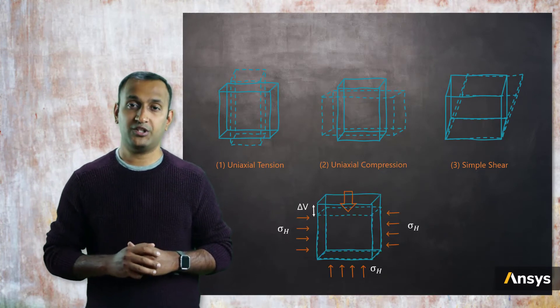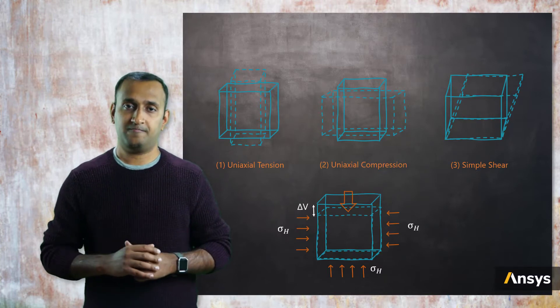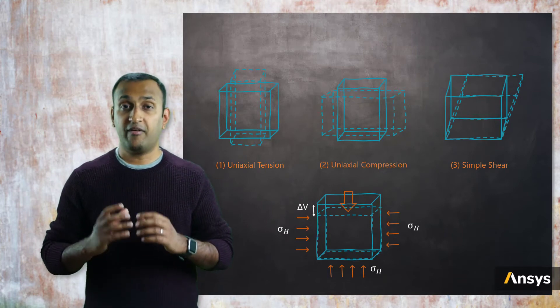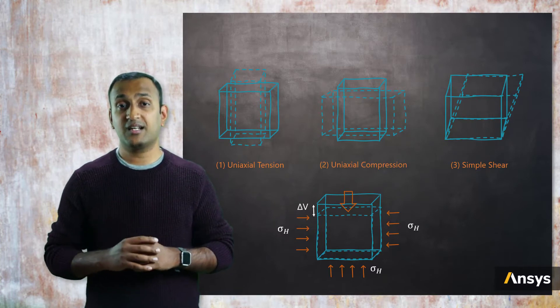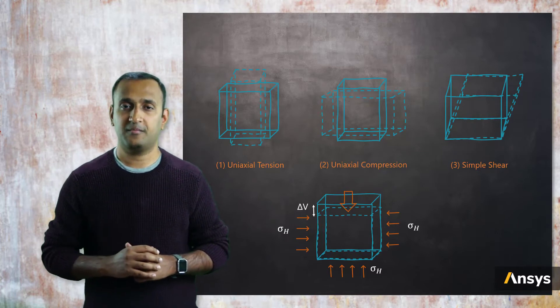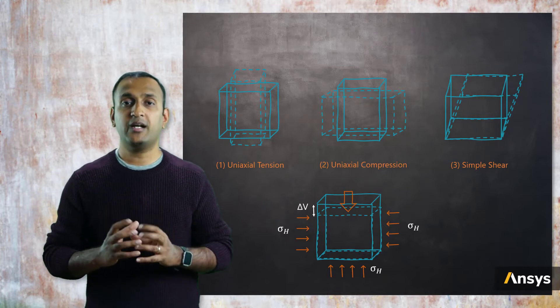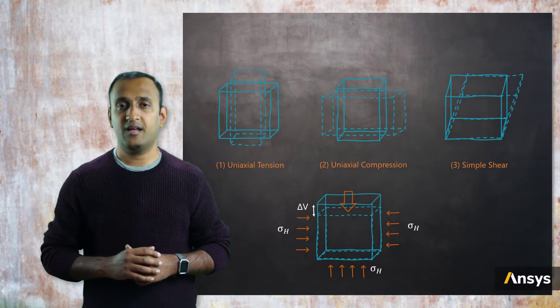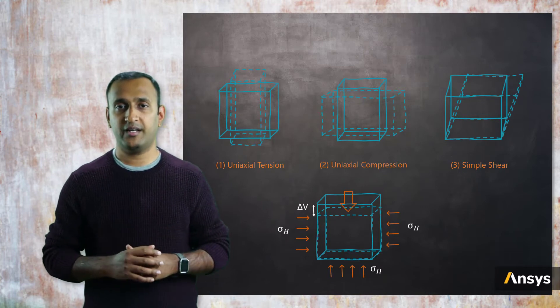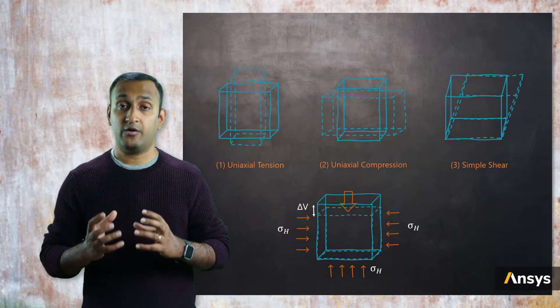There is a fourth mode of deformation which also needs to be measured to calibrate the volumetric behavior. In this case, the material is subjected to confined compression, where the material is constrained from deforming in all directions except the loading direction. This way, the stress state created in the material is predominantly volumetric. The change in volume is calculated from the applied load, and the hydrostatic pressure is measured using load cells to obtain the hydrostatic pressure generated due to a controlled change in volume.